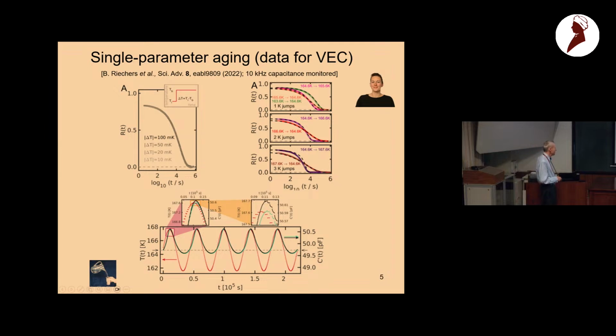What really impressed me was that the first cycle here is not identical to the second one. That's because of the initial condition: we start here at t equals 0, so it's not a steady state until a few cycles later. And even the deviation here is reproduced by the theory. Okay.